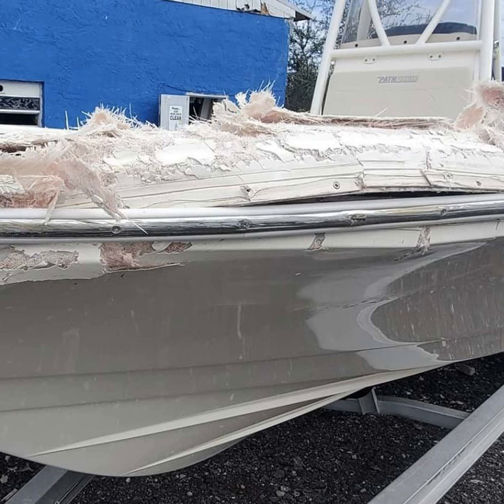If it's an older boat and you really want to try to get some really good adhesion and you've got a budget to get the best materials, then you can use vinyl ester resin. Vinyl ester is a significantly better resin than polyester. It has more corrosive resistance. It also has less shrinkage, and it's overall just much stronger. If you leave 2 inches of resin in the bottom of a cup and you do one with vinyl and one with poly, and you slam them both on the ground, the vinyl is going to take 5 to 10 tries before we break it, and the poly is shattering on the first try. It's nothing against poly. It just shows you how strong vinyl is.